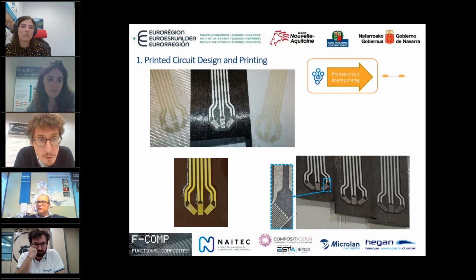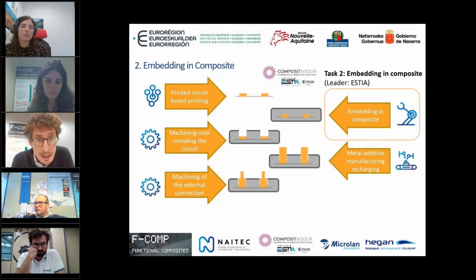The left one is fiberglass. In the middle is carbon fiber. Paper on the right. Bottom left is Kapton, and bottom right you can see 3 samples done in carbon fiber with the detail of the 70 microns track. We took these almost 200 samples to COMPOSITADOUR, so they can start with the embedding in the composite.